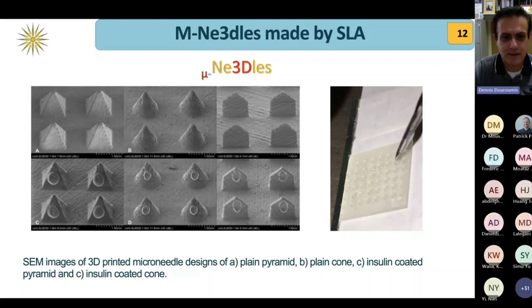Yes, please. Okay, so those microneedles here, you can see that on the top image we have empty microneedles. The bottom images we coat the active formulation on the surface, by using this inkjet printing. On the right image, you can see that this is an inkjet printer, and we can design the algorithm to coat the material on the surface without any losses or any satellite material going onto the substrate.